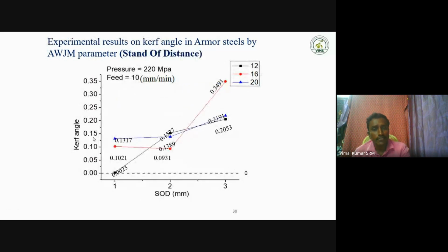Next is the standoff distance. Here we fix the pressure and feed and change the SOD. If SOD changes, the kerf angle changes, which means the SOD also influences the material. Absolutely, if we increase the standoff distance, the kerf angle definitely increases. For example, when we open our home tap, the water at the start comes out straight. If you increase the distance by one or two feet, it becomes tapered. The same condition occurs in the water jet machining process.